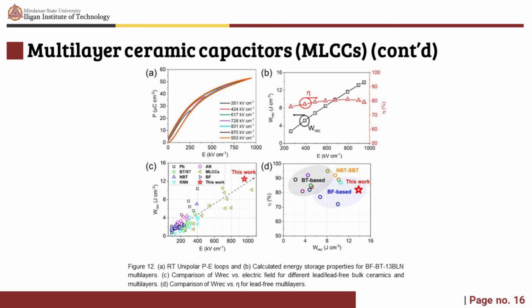Figure 12a to b. Pmax of 52 microcoulombs per centimeter squared and Pr of 4 microcoulombs per centimeter squared are obtained for multilayers at 953 kilovolts per centimeter. The energy storage properties of multilayers are significantly enhanced with respect to monolithic ceramics, yielding a record high of 13.8 joules per cubic centimeter with efficiency of 81% at 953 kilovolts per centimeter, which is the highest value to date for lead or lead-free ceramics and multilayers as shown in Figure 12c to d, fabricated using a scalable powder-based technology.